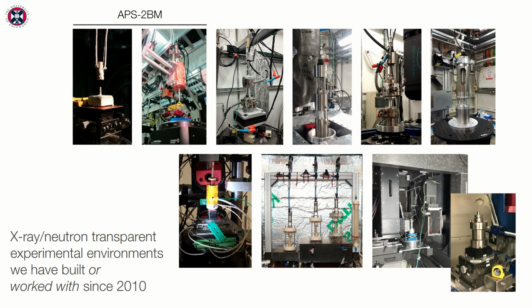And we started with very simple experiments here. So at the time, Shangwei supported us in building an X-ray transparent furnace. That was a very simple furnace here, but it produced actually quite nice data. It allowed us to vary the temperature around the sample and look at certain temperature activated processes such as thermal cracking or dehydration. That furnace evolved massively, and a couple of years later it looked like this, and it was super powerful and very efficient.